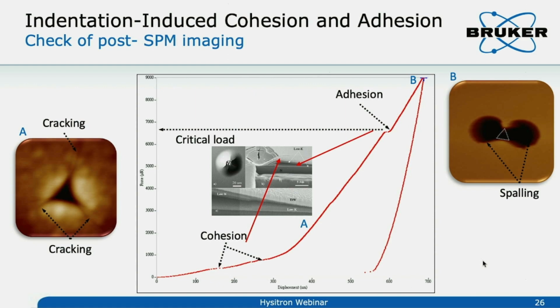So if you look at the cross-section or the SEM image, you can see the cohesive crack usually happens first. Then the second pop-in is the delamination under the surface. Maybe you cannot see it from the surface, but if you cross-section, you see the delamination happen. So that's very interesting for me. If you have crack pop-in, you can use a model to calculate the fracture toughness. If you see the delamination, you can use the model to generate the adhesion work, adhesion measurement.